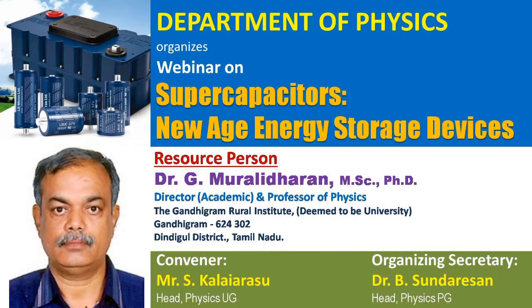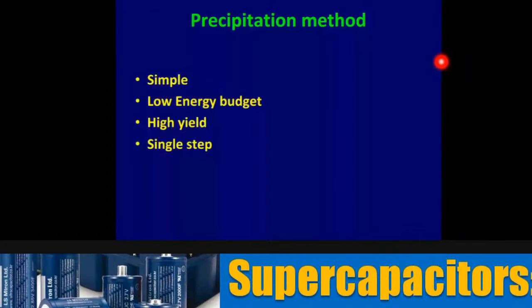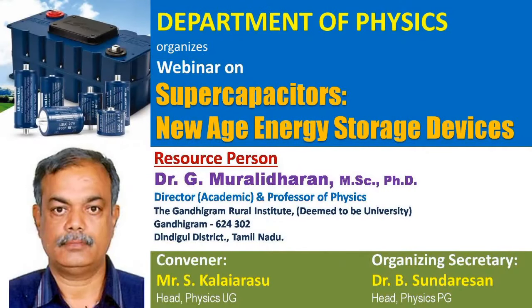So as I was telling you, in the precipitation method, we have a simple, low budget method. We have used it for nickel hydroxide synthesis. Nickel nitrate is the starting material. The stabilizing and capping agent was starch. Glucose acts as a stabilizing agent again. Double distilled water and a little bit of ammonia were added, and that gives us excellent nickel hydroxide material.